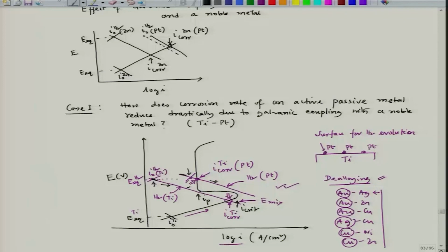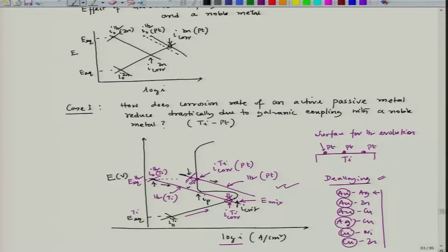That means the current density difference between these two lines would be very large, and if you take log scale for these current densities, the addition of the hydrogen evolution reaction on the titanium surface would have very minimal effect on the hydrogen evolution reaction on platinum surface. So that is what I have not added, but you can also add it, and that addition will be very close to it, almost merging on top of the existing cathodic line on platinum surface.